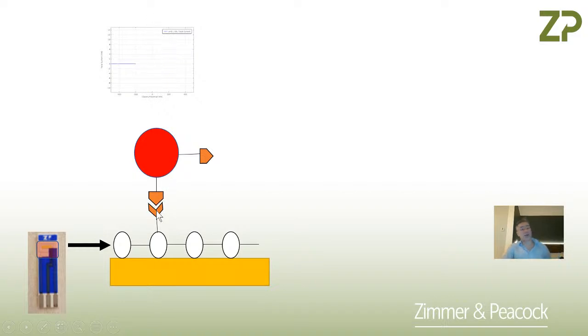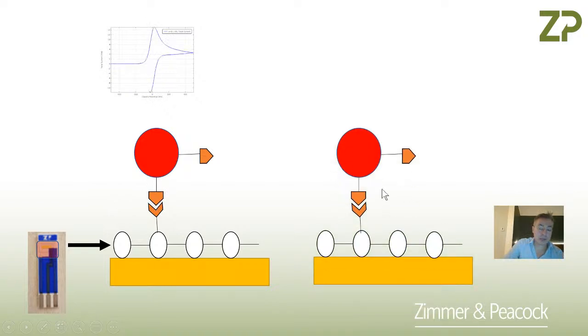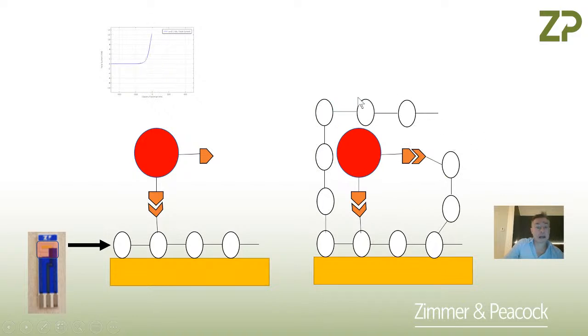But now we have the idea that the template is going to become encapsulated or embedded within the electropolymerized polymer. But it's not just that the polymer is taking the shape of the template, it also has functional groups that have a specific interaction with it. And I think that really then helps with the specificity. So when I think about drug molecules, they often have a lot of functional groups on them. So I can see that a molecular imprinted polymer really works best with, let's say, targets that have more functional groups. And then when you wash it away, you're left with a molecular imprint, but you've also got specific functional groups in that pore.